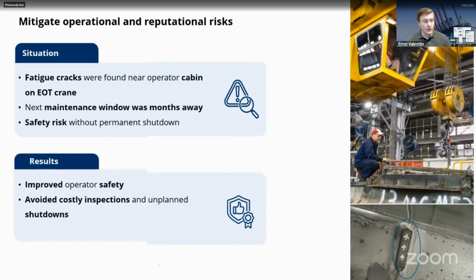In this case, after only 1 or 2 months, we noticed a lot of very rapid crack growth on these sensors. In some cases, to the point I would say we have stopped seeing these cracks because they've grown so fast, so far, they have grown out of the range of our sensors already. This is worrying. This asset owner then stopped the crane, went back onto the crane to do an additional inspection, and indeed found that all of these cracks were growing at a very worrying rate, to the point where they could no longer vouch for the safe operation of the crane. So they stopped the crane, took it out of operation, and did repairs at an earlier point. In this case, just greatly increasing the operator safety for the people working in that crane and managing to flag a potential accident quite early.